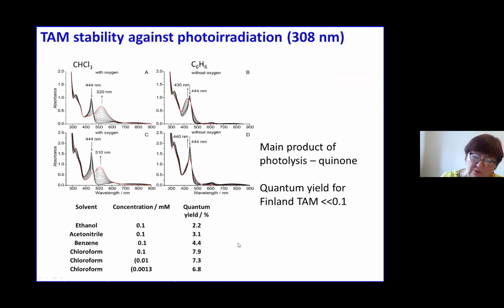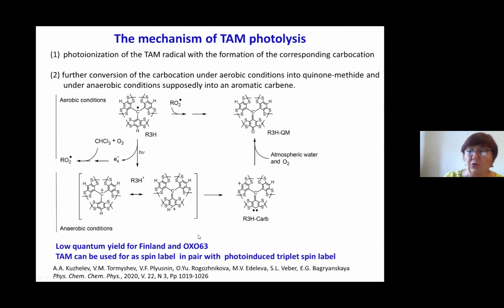And the main aim was to see if it's possible to use it. And it was confirmed that quantum yield for photolysis of the trityl radical is very low. That means trityl radical can be successfully used as a spin label for such kind of experiment when the partner is a photoinduced spin label. And also, in addition, we investigated the mechanism, and the mechanism of the photolysis is the following. It is photoionization of TAM radical with formation of the corresponding carbocation, and then its transformation. We propose that it is such a carbocation, and then with atmospheric water, it forms